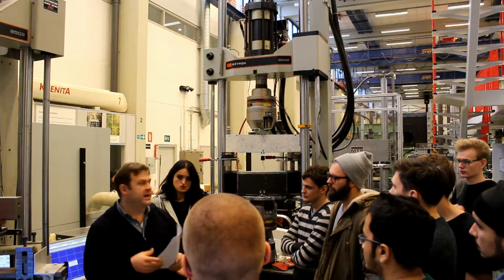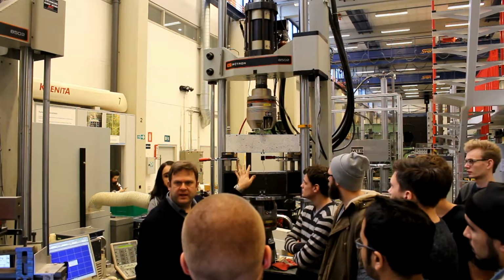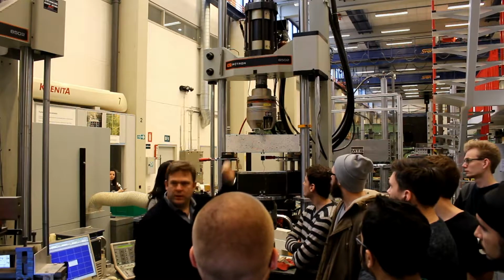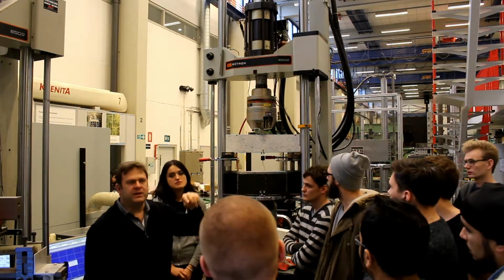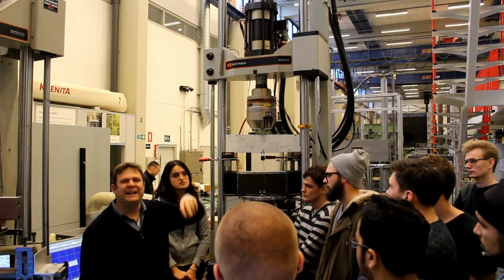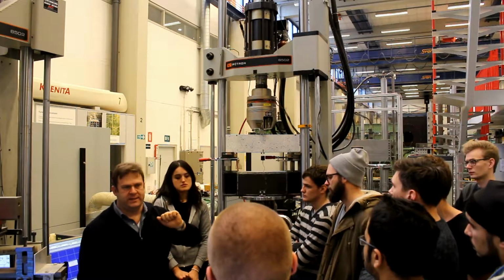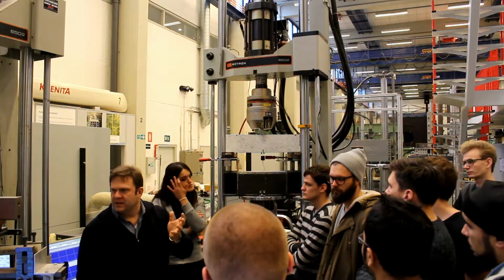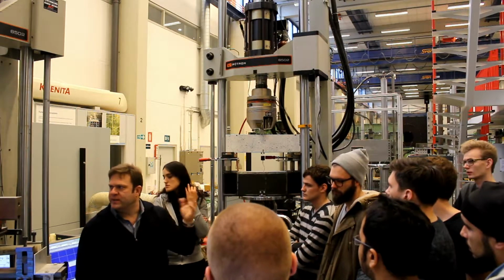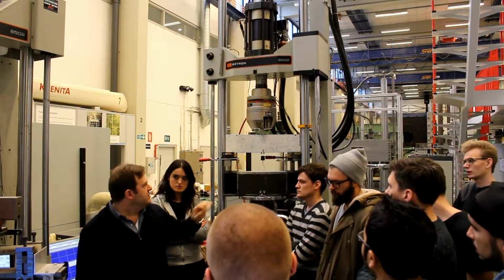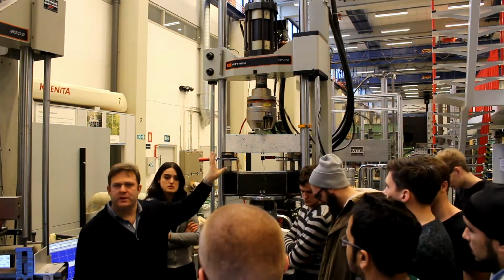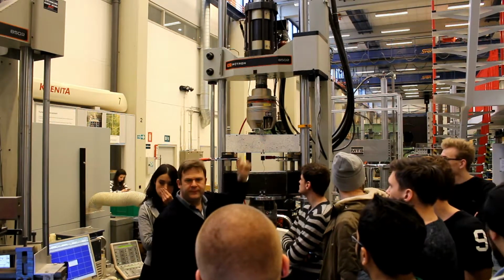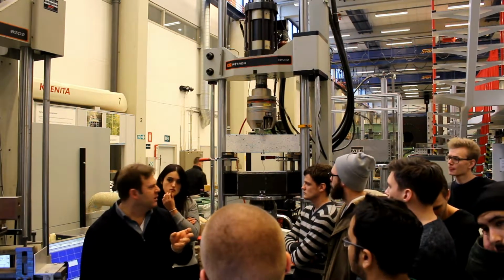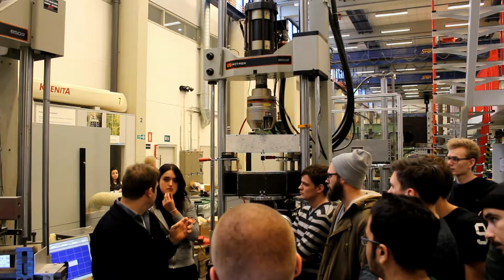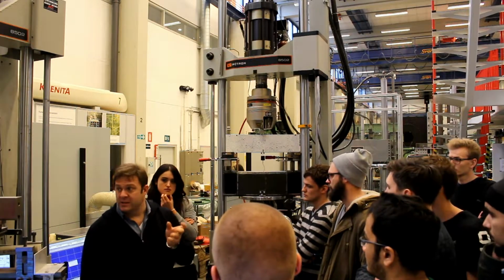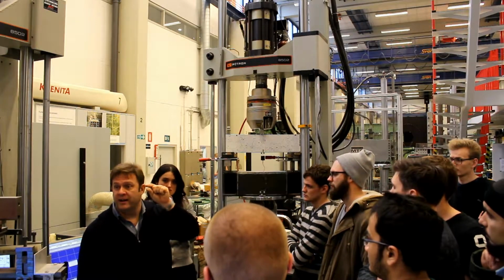In this standard here, there is an explanation of how fast you want to run that test. This is also standardized. So the configuration is standardized, like the span and where to apply the load, how to cut the notch, but also we have a guideline on how fast to run that test. We don't want to run it too fast because then we might not be able to capture the important details that we want to see. So in the beginning, especially before the first crack occurs right here, we will run the test very, very slow. How slow? 0.05 millimeters per minute. So 50 microns, half the size of your hair, per minute.